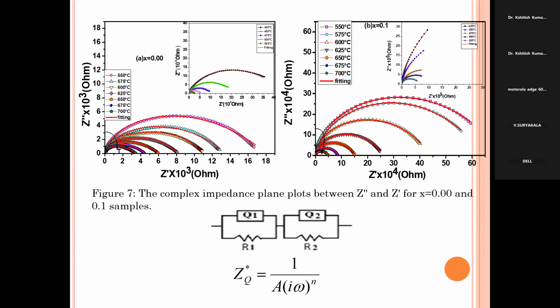And this one is the Nyquist plot. Here we have plotted the graph of Z prime, Z double prime, and from that we calculate the resistance of the grain and the resistance of the grain boundary, and how they are related to temperature. We have conducted the measurements from room temperature to 700 degrees centigrade. As I told, my material sustains up to 530 degrees centigrade, or the transition temperature is 550 degrees centigrade. So we have taken from room temperature to 700 degrees centigrade, and we also found how the grain and grain boundary resistance are related to the structural property, the ferroelectric property, and the piezoelectric property. All the characterization we have done, and we have correlated the structural parameters with the electrical property.